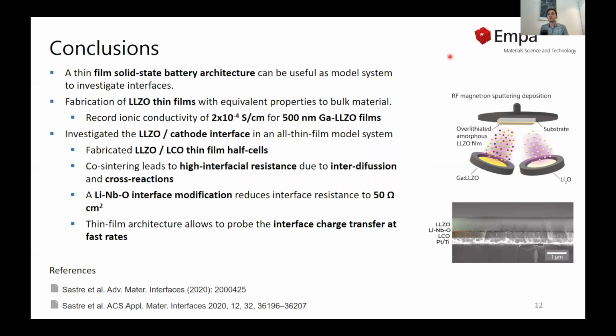So with this, I would like to conclude my talk. I've shown you that thin-film solid-state battery architectures are useful model systems to investigate interfaces. We developed a method for fabricating LLZO thin films with equivalent properties to the bulk material. Specifically, we were able to demonstrate ionic conductivities of 2 × 10⁻⁴ Siemens per centimeter in a 500 nanometer gallium doped LLZO film. With this fabrication process, we were able to construct an LCO thin film model system that we employed to investigate the degradation processes occurring at the interface upon co-sintering. And we also used it as a playground to investigate interface modifications.